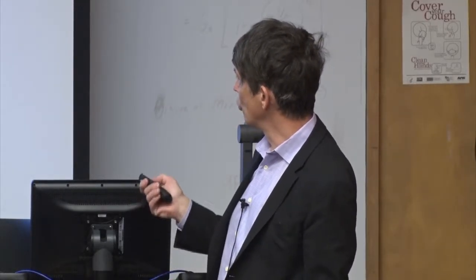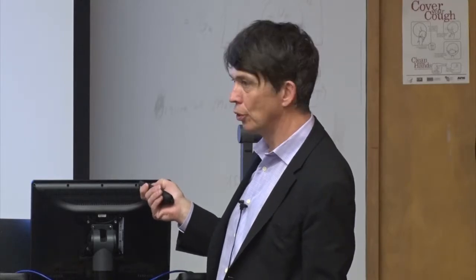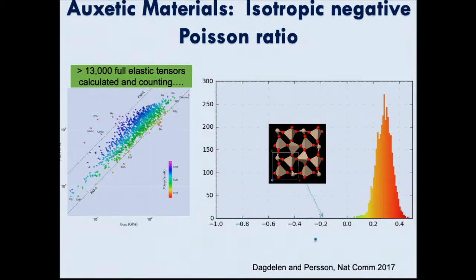And if you look at known compounds for which the properties are known, like the Poisson ratios are known, this is the distribution of the Poisson coefficient. And of course, it's around a third. It peaks because that's the most common Poisson ratio. But there's actually one material in here. You can't even see it. It's because there's only one material, and it's silicon dioxide in the alpha cristobalite structure.